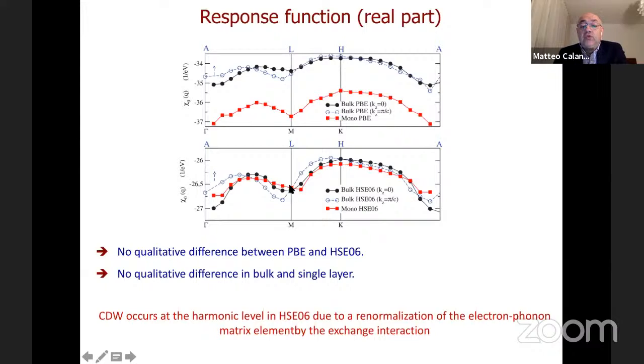You can see that with respect to the other points on the same curve, there is a softening around the point M, but the magnitude of the softening is almost identical in monolayer with PBE and HSE06, despite the fact that PBE has practically no softening and HSE06 has a big softening. So this means that the softening is actually due to the matrix element and to the fact that the exchange interaction renormalizes the matrix element, so the electron-electron interaction has a strong effect on the derivative of the self-consistent potential in density functional theory.